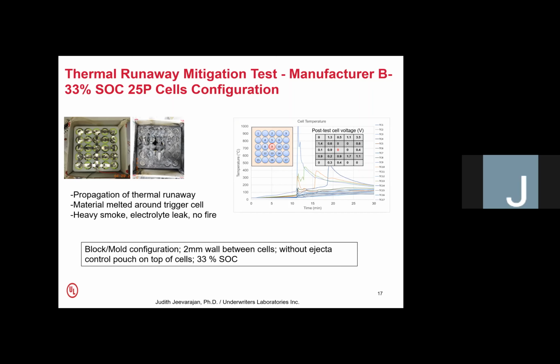And we got a very controversial result in the sense that it propagated completely to almost all the cells. The interesting part was that after that initial cell went into thermal runaway, again, this is only at 33%, even the trigger cell is at 33%, we found that at a certain point there was heavy smoke and electrolyte leakage. When the test was complete and we looked at the test setup, we found that there was a lot of electrolyte leakage on the test table, and I think that is what contributed to the heat spreading to the other cells and also to the heavier smoke that we observed. But of course, we didn't see any fire because these are only at 33% state of charge.